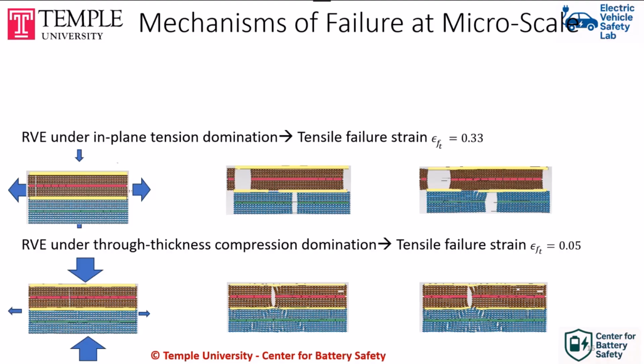Now, if we have compression between the layers, then the deformation can be localized. When we have the failure of the metal current collector, the deformation will happen locally right under there, and then the separator failure will happen very quickly upon metal collector failure. So the failure strain in this case for short circuit will be more equal to the failure strain of the metal, 0.05.